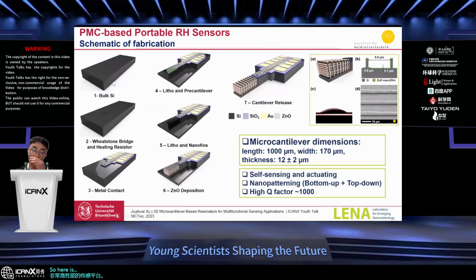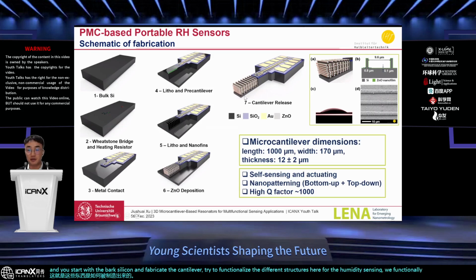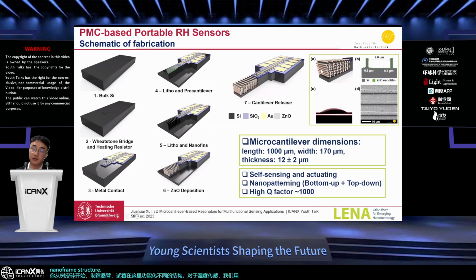So here is how the sensor has been fabricated. You start with the bulk silicon and fabricate the cantilever, and try to functionalize it with different structures. For the humidity sensing, we functionalized the cantilever with a nanofin structure. And here the zinc oxide nanoparticles have been selectively deposited on the cantilever as a sensing film. I will not introduce the whole process in detail. If you are interested, you can find the paper, or you can write to me. We can also talk in detail.